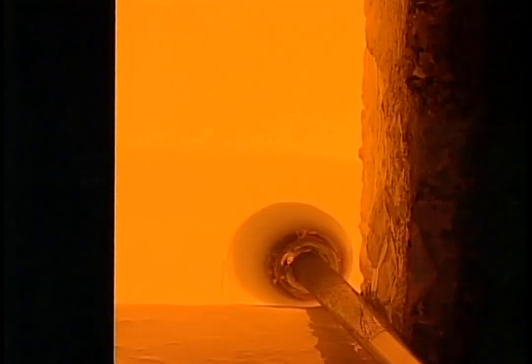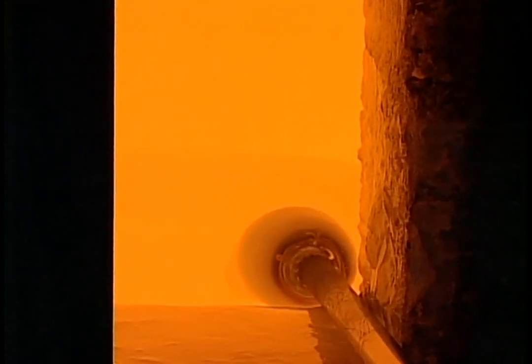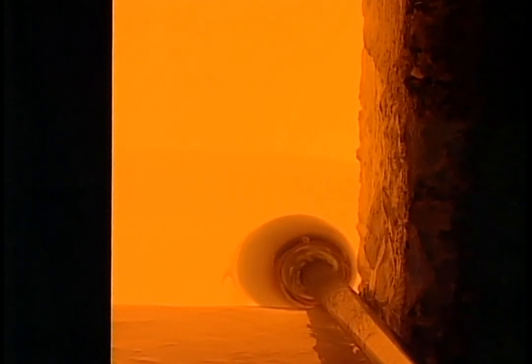The temperature of the furnace has to be brought up to 2,400 degrees, that's a place where the batch will actually melt into clear glass. At the end of the day, it's cooked another 3 or 4 hours and then turned down to low. And overnight, cooling back down, it's ready to use the next day. That's where the glass is melted to kind of the consistency of honey.